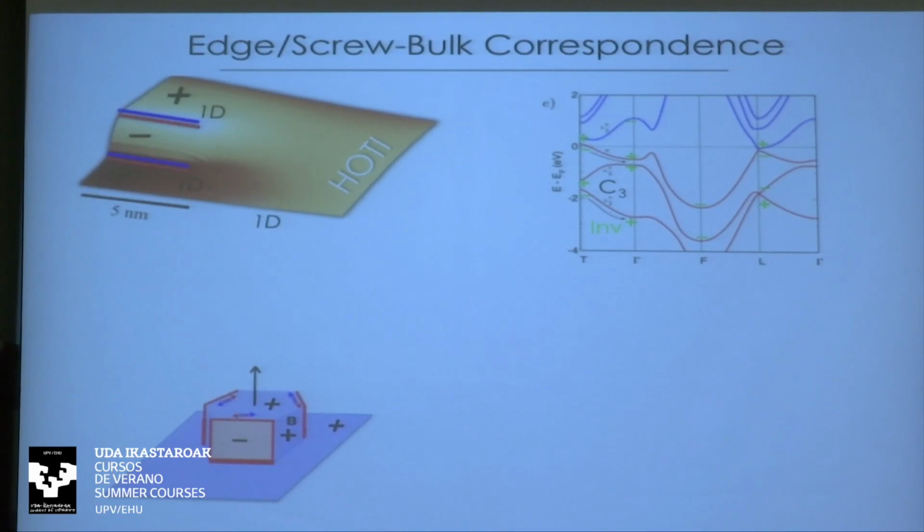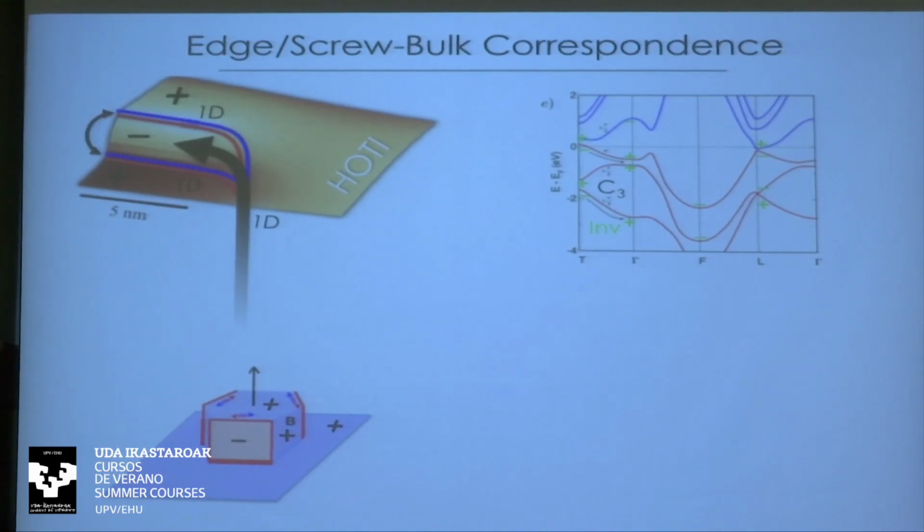But on the other hand, this is a very clean step edge. So the fact that they are separated only by 4 angstrom doesn't necessarily mean that they have to be heavily hybridized. Of course, if this were a higher step edge in height, they would be further separated away, and then definitely they wouldn't have to hybridize. But if you're willing to take that these two don't hybridize, although they're separated only by 4 angstrom, once they plunge into the screw dislocation, they really sit one on top of the other.